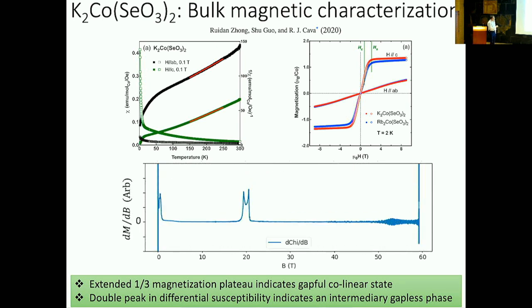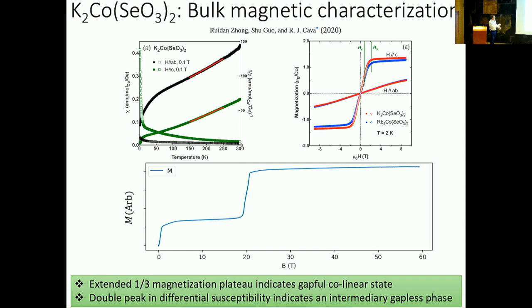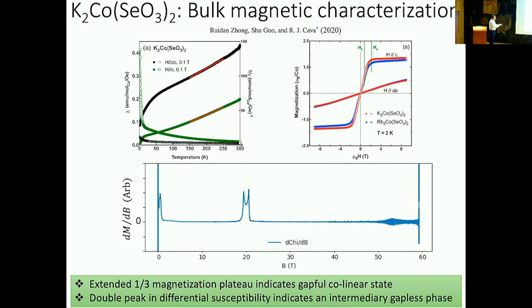Now, if you look at dM/dB as a function of B, so it's the same data, I just take a derivative. And if you look very, very carefully, you can see something is not quite right about this guy here. When you take the derivative, there are actually two peaks. That was just amazing to see. It indicates that there are actually two different phase transitions. This peak is the final coming up to the fully saturated system, but there's something taking place a little bit lower, and in between there is a compressible phase, which we think is actually a supersolid state.